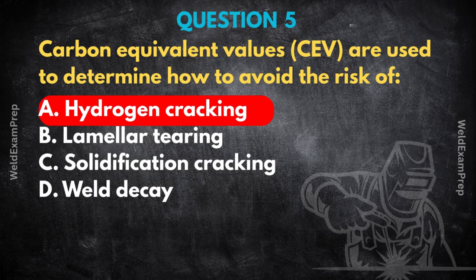And just quickly, why not the other options? Lamellar tearing. Lamellar tearing is more about the steel plate itself having poor ductility in the through thickness direction, often due to inclusions. It's related to joint design and material quality, not directly predicted by CEV in the same way. Solidification cracking. That happens during freezing in the weld pool itself. It's driven by weld metal chemistry, things like sulfur and phosphorus content, and how much restraint is on the joint. Again, different mechanism, not CEV's main job.